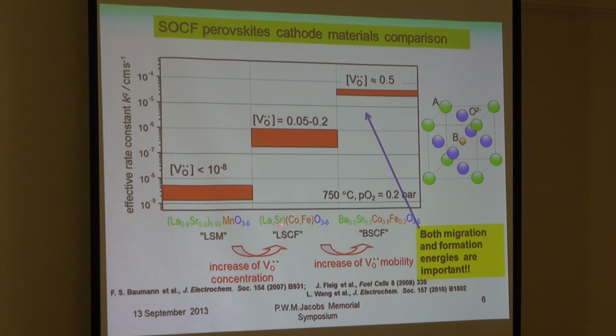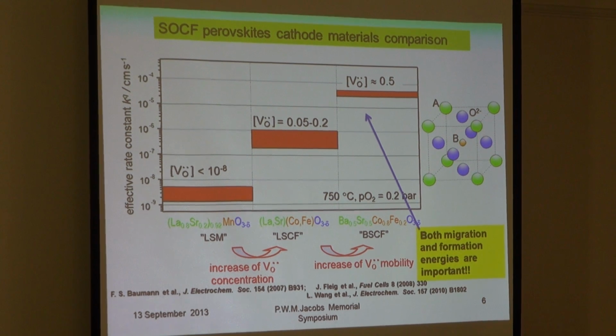Next, more complicated, when we have a solid solution, then on the A site of the perovskite lattice, we have lanthanum and strontium. On B, it's cobalt and iron, so it's called LSCF. And the most efficient material nowadays is barium, strontium, cobalt, iron, which is called BSCF. And essentially, if you look at this, just efficiency, you can see that